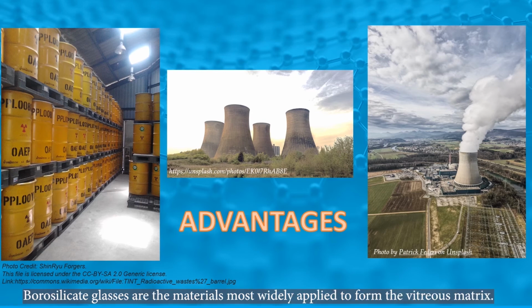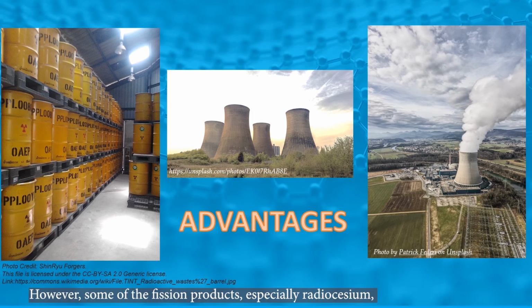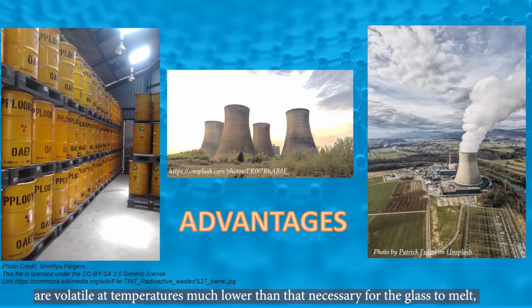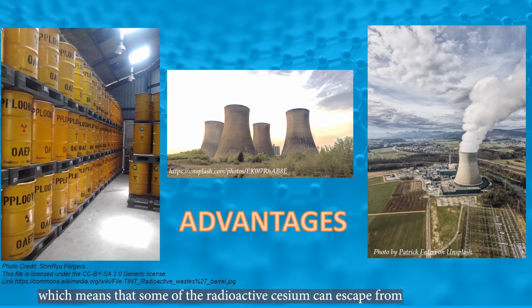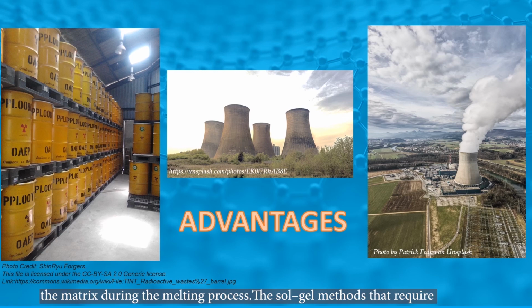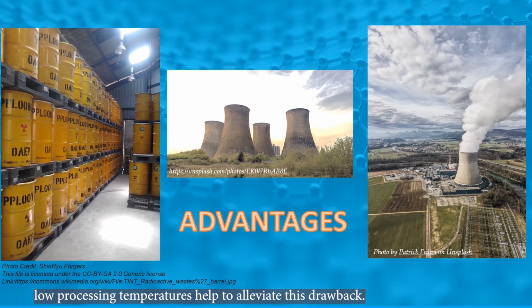Borosilicate glasses are the materials more widely applied to form the vitreous matrix. However, some of the fission products, especially radiocesium, are volatile at temperatures much lower than that necessary for the glass to melt, which means that some of the radioactive cesium can escape from the matrix during the melting process. The sol gel method, which requires low processing temperatures, helps to alleviate this drawback.